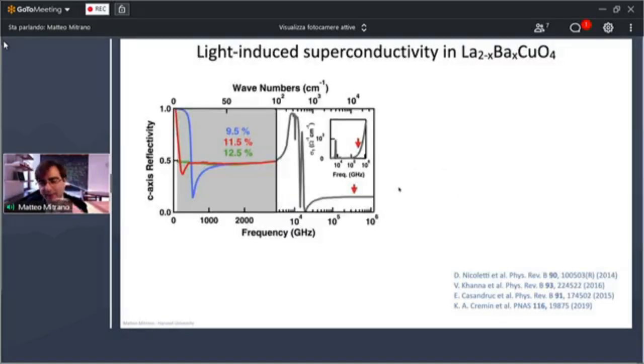This material is particularly interesting because at equilibrium, superconductivity at 1/8 doping is strongly suppressed by the presence of a competing order. The way we detect superconductivity in this material is by looking at the reflectivity. This is the reflectivity along the z-axis, and we can see that when the sample goes superconducting, there is a plasmon along the z-axis that corresponds to the tunneling of Cooper pairs along the out-of-plane direction. These are layered materials, and you have transport along the out-of-plane direction.